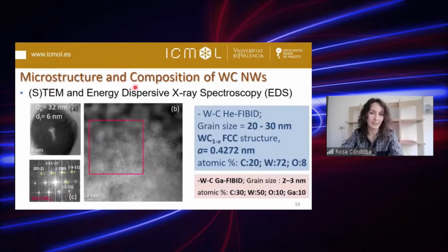Regarding the microstructure and the composition of these tungsten carbide nanowires, we have to mention that the grain size is around 20 nanometers, and the crystallographic structure of these grains perfectly fits with the tungsten carbide FCC structure, and the composition is very good. I mean, we obtained 72% of tungsten, and here you can see, as a comparison, the results that we already obtained in tungsten carbide wires using gallium focused ion beam, where the grain size is much smaller, and the tungsten content is smaller than in the case of using the helium beam.